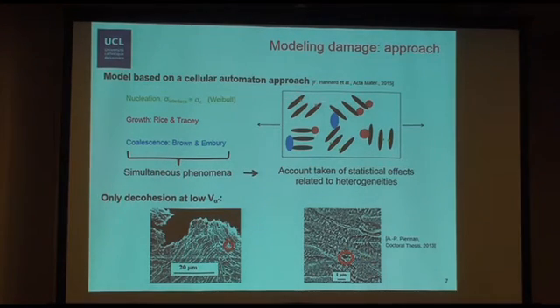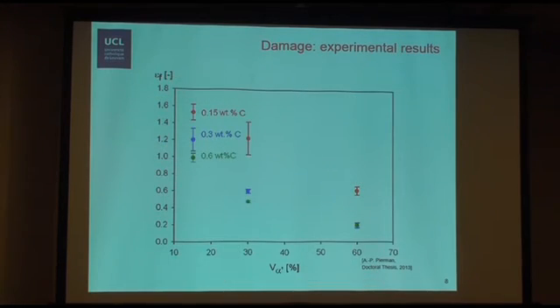You see the green dots here always appear at the interface. And this choice is justified by the fact that at low martensite volume fractions, it's always decohesion that is observed, like you can see on those micrographs at two different magnifications. At higher volume fraction of martensite, particle breaking occurs. Then it's possible to tune the model by incorporating another Weibull law for particle breaking. It will be done.